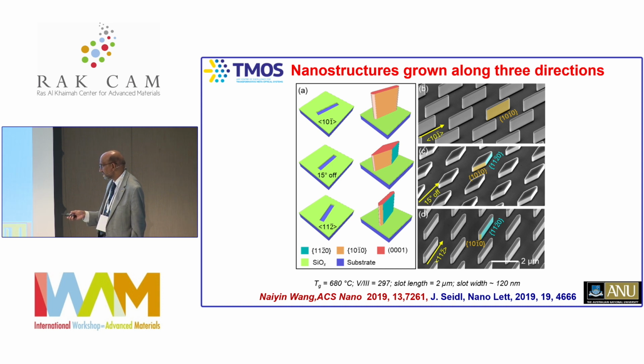Also, these membranes are thicker than these particular ones because of the lateral growth which is taking place. But if you open the slot in between these two orientations, then what you end up having is these beautiful diamond-like structures with these alternating facets. So now you can see, instead of just making nanowires, we can make thin membranes, thick membranes, and diamond-like structures.